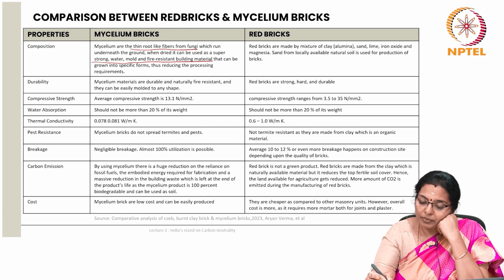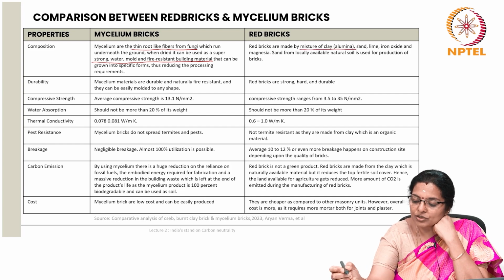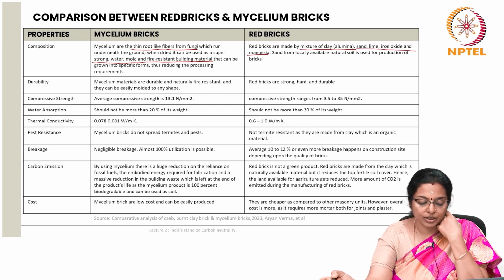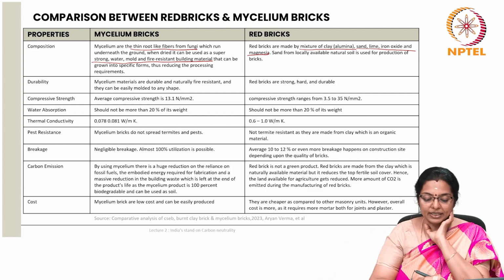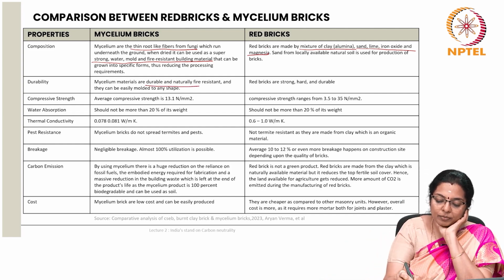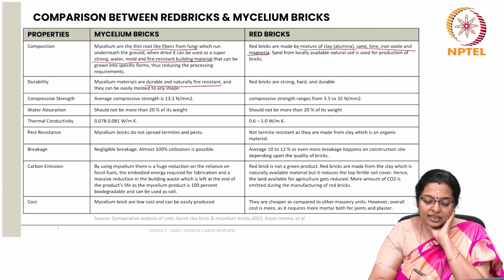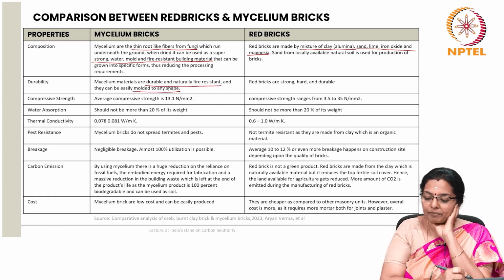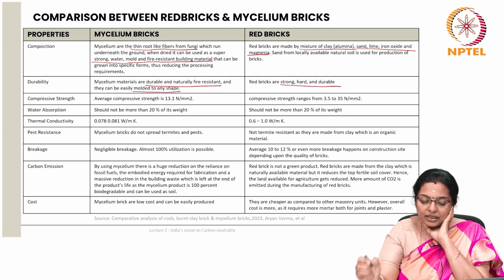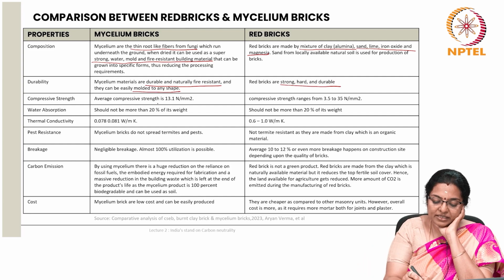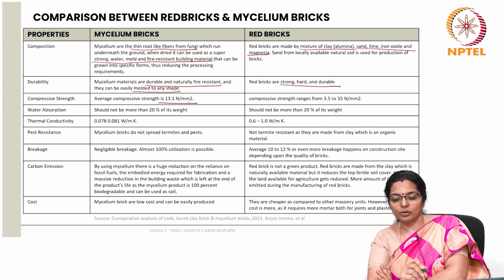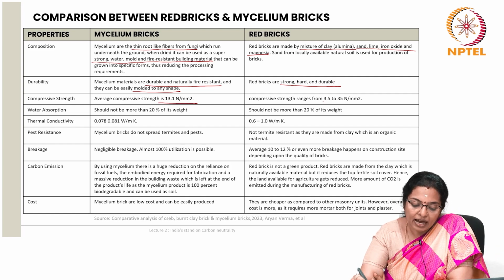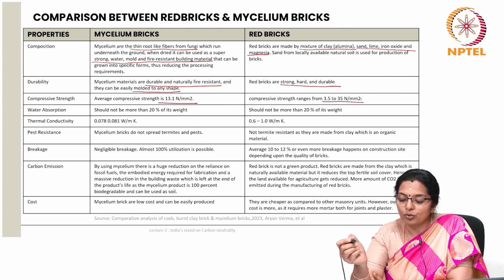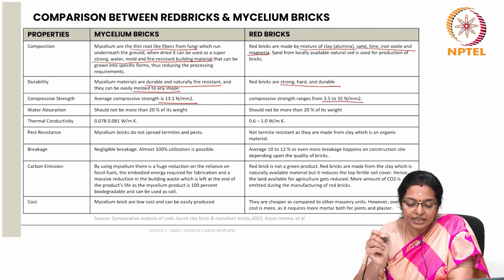Whereas the regular bricks are made from a mixture of clay, which is alumina, sand, lime, iron oxide and magnesia. Sand from locally available natural soil is used for production of bricks. In terms of durability, mycelium materials are durable and naturally fire resistant, and these can be molded into any shape. Red bricks too are strong, hard and durable. Mycelium's compressive strength is 13.1 Newton per millimeter square, whereas red bricks have a compressive strength of 3.5 to 35 Newton per millimeter square.